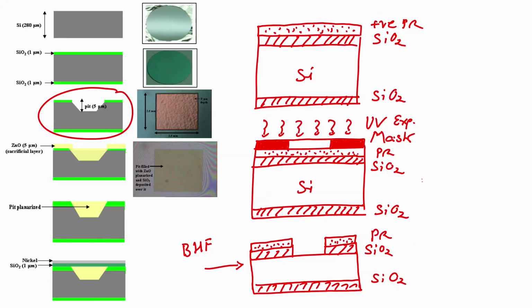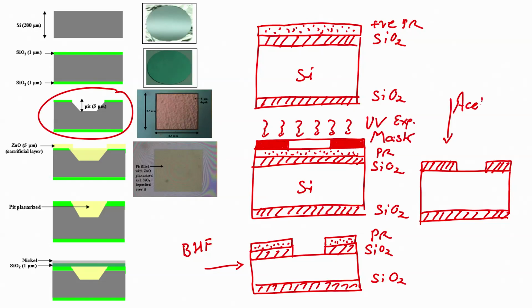After this, the next step would be to remove the photoresist. So, dip the wafer in acetone. When you dip the wafer in acetone, the photoresist will strip off. And then again the question would be, when you dip the wafer in BHF, will the back side get etched or not? SiO2 on the back side can get etched. So, we can protect the back side by spin coating photoresist.